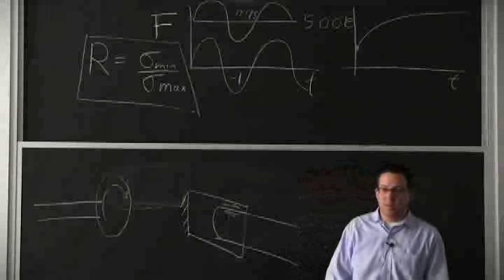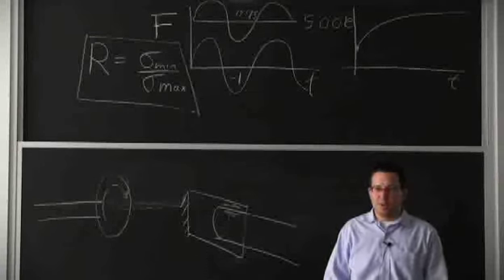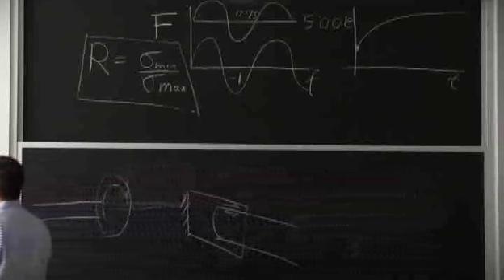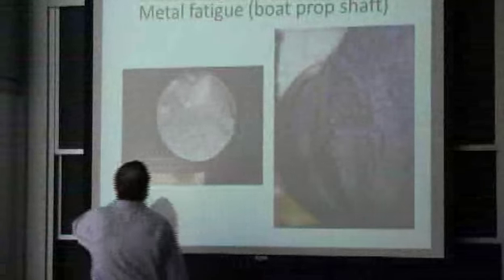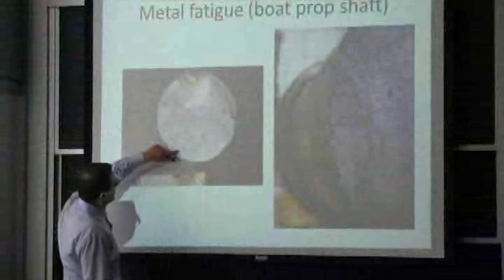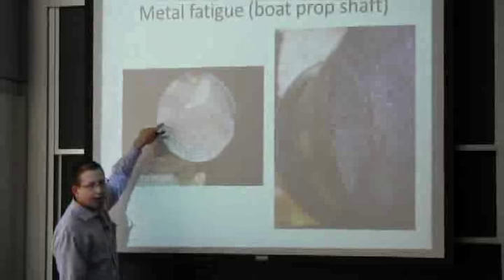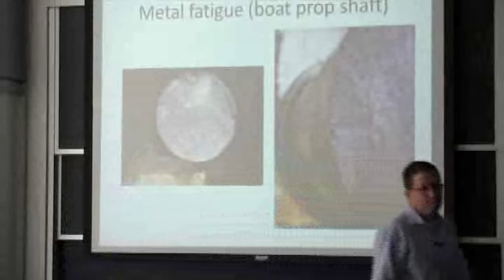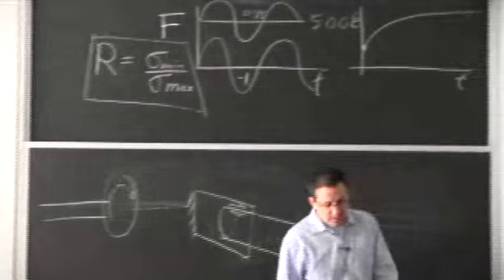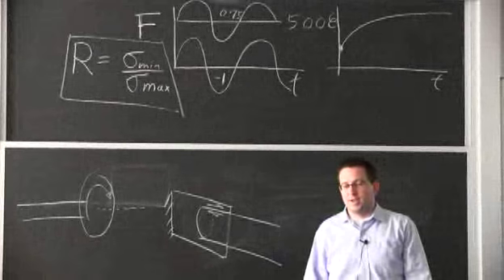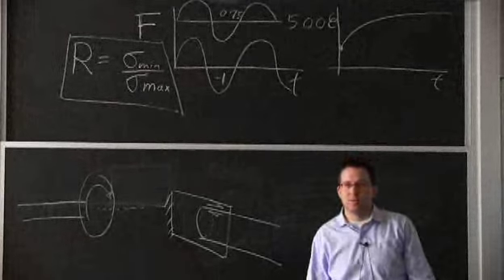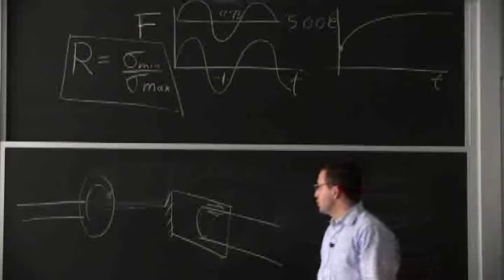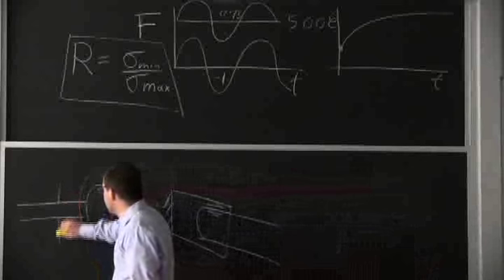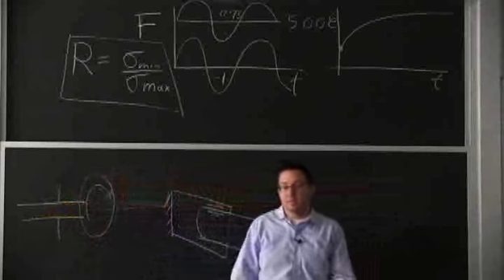So that gives us some idea of what's really a bad flaw. This is a bad flaw because we only have one crack that started here. It went all around up to the middle and overloaded. If we had a bunch of small flaws, what will happen right here is you'll have a little circle around here, another circle around here going towards the inside, a little bit like we had with the plastic pipe. That's the big difference. So the flaw size in this case was large. It wasn't so much of a material flaw because there was wear. There was wear between all the gasketing system here of the boat and the outside, and that created that flaw.